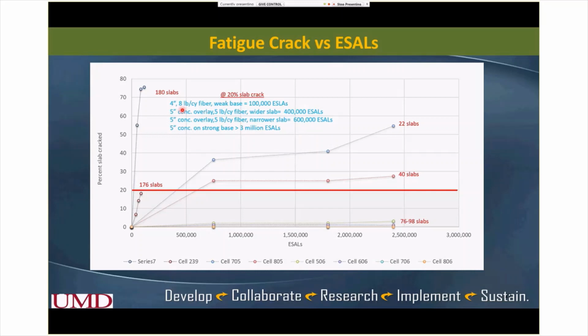4-inch thick with 8 pounds per cubic yard fiber, but a weak base. It took about 100,000 ESALs, sorry about the spelling here, to reach 20% slab cracked. And for the 2 overlays, the wider slab one reached 20% slab cracked at 400,000 ESALs, and the narrower one at 600,000 ESALs.